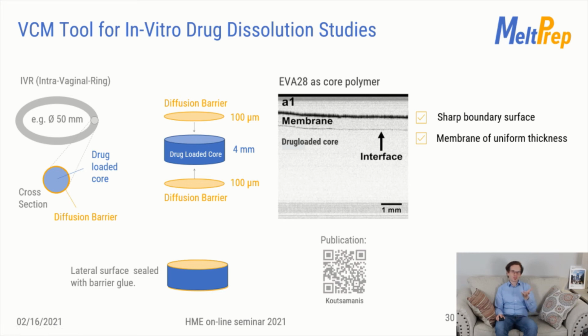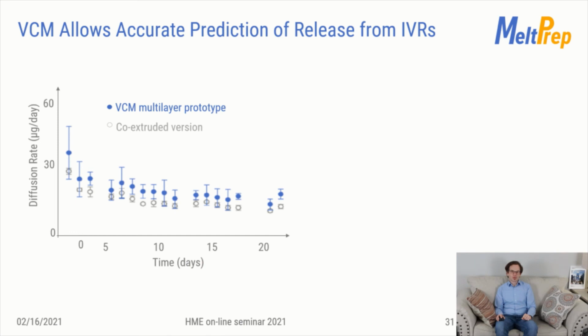The final VCM sample that they ended up with was a sandwich of two 100 micrometer thin diffusion barriers filled with a drug-loaded core. Then they covered the lateral surface with barrier glue, used optical coherence tomography to check for the interfaces and see if the diffusion barriers are uniform in thickness. And afterwards, they subjected the samples and a co-extruded version to dissolution. So what you see here, this is giving a very good match.